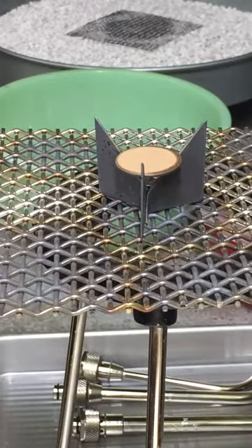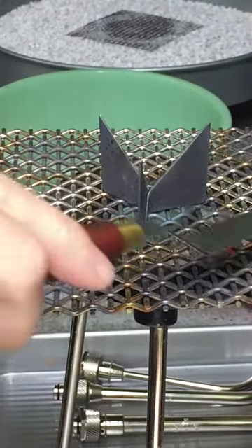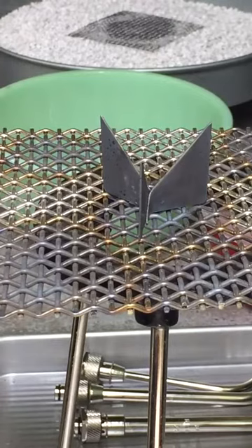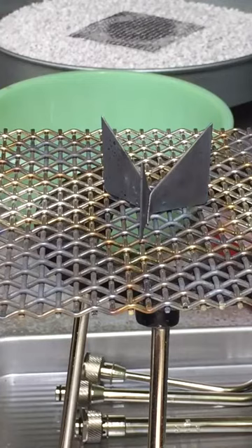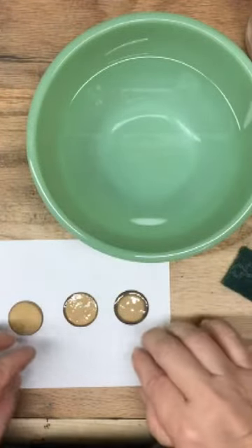After the piece is cooled a little bit, go ahead and remove it from the trivet with your palette knife and set it off to the side — I like to set it on the mesh screen in a corner. A couple of things about this process: you don't want to quench the enamel by putting it in water, as it will crack. This is still extremely hot. If you set it on a cooler metal surface you do run the risk of it cracking, so on that final fire definitely watch how fast you're cooling your enamel.